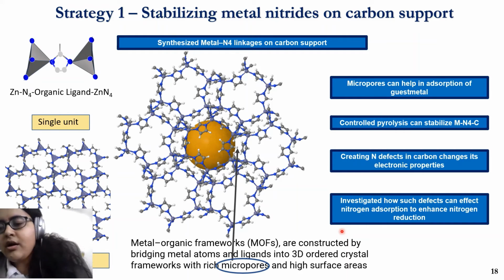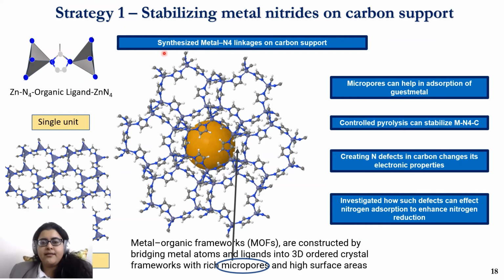So then we thought of utilizing metal nitride linkage on a carbon support. These are called metal organic frameworks, wherein the single unit, let's say, is formed with zinc nitrogen linkage. These can form the building blocks of a metal organic framework, which will have huge pores. And these micropores actually help in the adsorption of the guest, which could be nitrogen in this case. And we can pyrolyze this metal organic framework to get metal deposited on a network of carbon structures. And then the defects can affect the nitrogen adsorption to enhance nitrogen reduction.